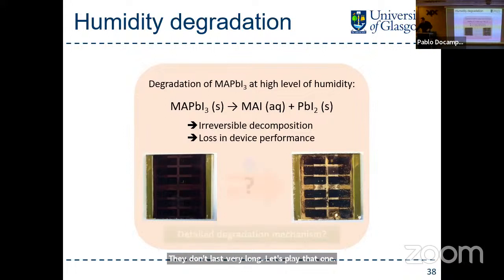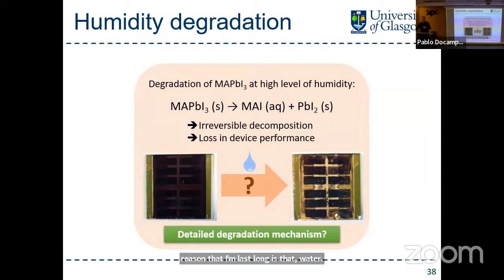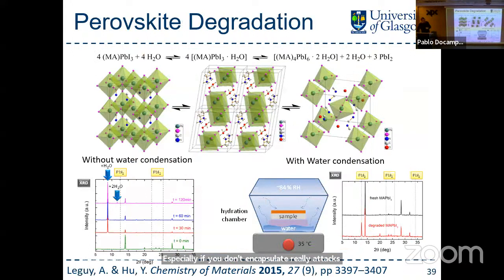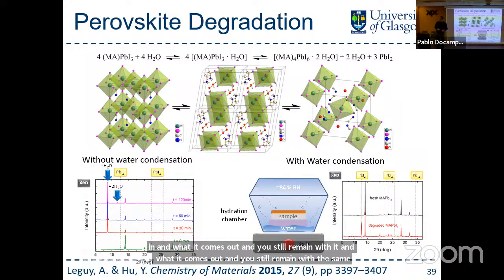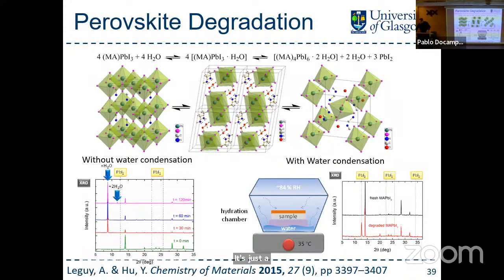The reason they don't last very long is that water, especially if you don't encapsulate, really attacks the structure. In some of our early work looking at this, we saw that water can actually be part of the crystal. You can hydrate these crystals and then disconnect the octahedra from the corners. As I was saying earlier, if you change the bond halide angles or the geometry of that bond, you lose your optoelectronic performance. So basically, when we hydrate the crystals, we lose conductivity and the rest. The nice thing that we did find out is that water goes in and water comes out, and you still remain with the same crystal structure. You actually recrystallize it by putting the water in.